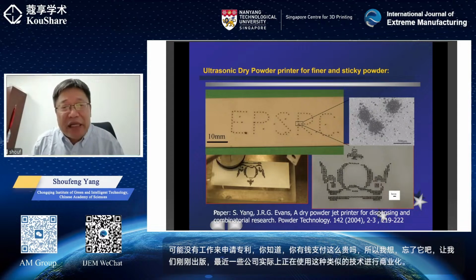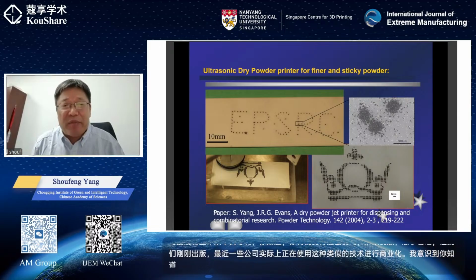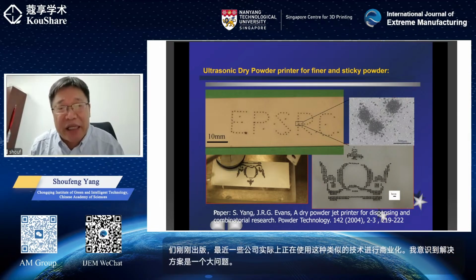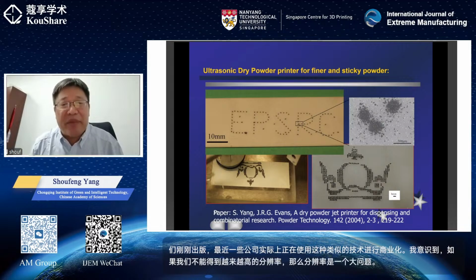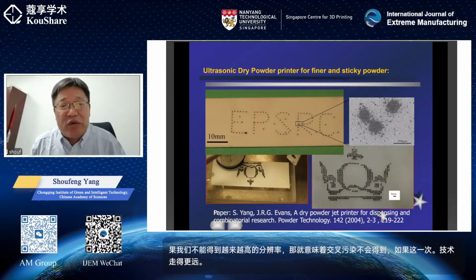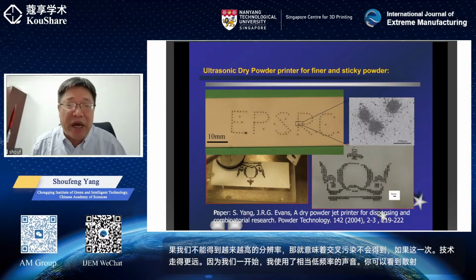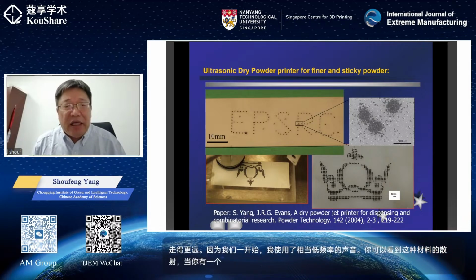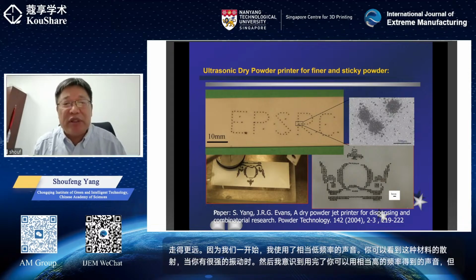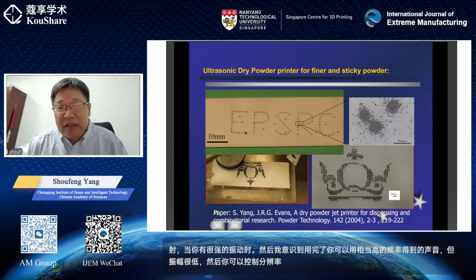And I realized that the resolution is a big problem. If we can't get resolution higher and higher, that means the cross-contamination won't let this technology go further. Because at the beginning, I used pretty low frequency of sound, you see the scattering of these materials when you have a pretty strong vibration. Then I realized, using ultrasound, you can use a pretty high frequency, but pretty low amplitude. Then you can control the resolution. At the time we could get pretty low, a few hundred micrometers of resolution.